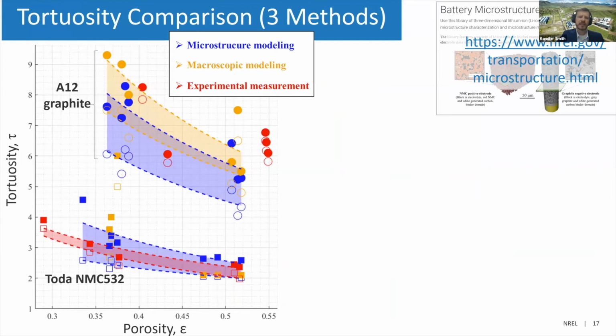In the case of, so this is an NMC material with more or less spherical particles. This is a platelet-like graphite material. The orange here are the macroscopic models. Here we have a lot of noise in the macroscopic models because at low tortuosities, you don't see much rate dependence on tortuosity. It's other things like solid state diffusion that dominate it. But we do see great agreement between the experimental measurement from Dean Wheeler as well as our estimation from the homogenization calculation or the microstructure modeling.